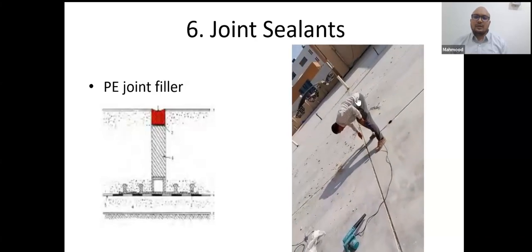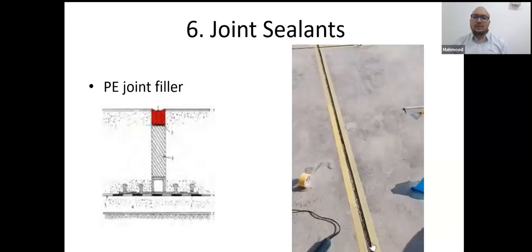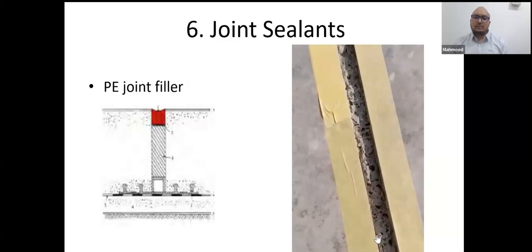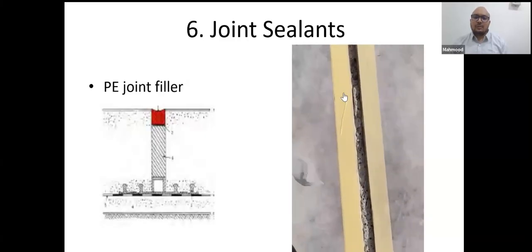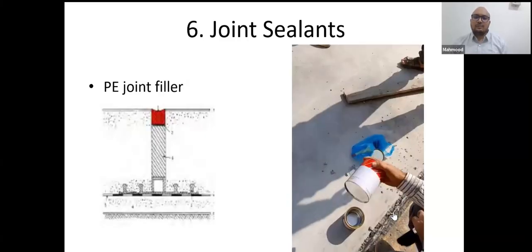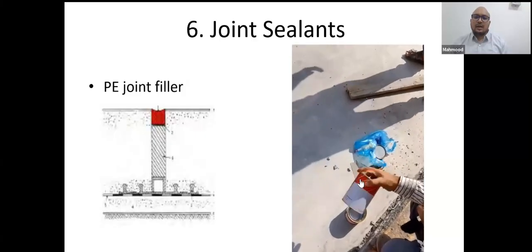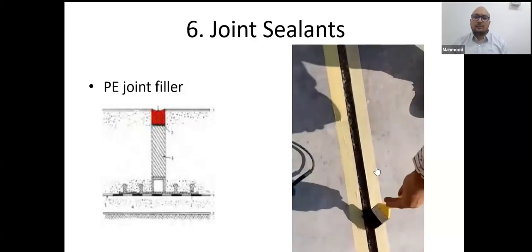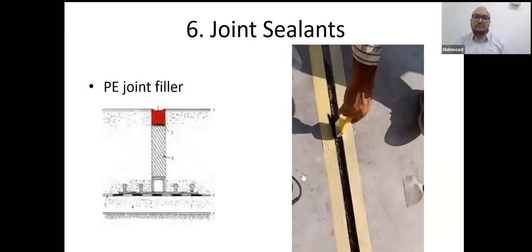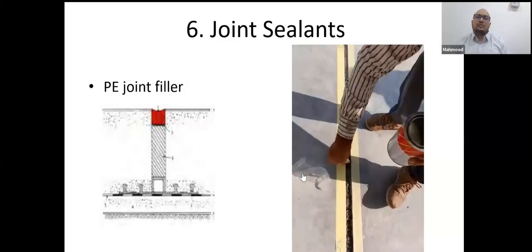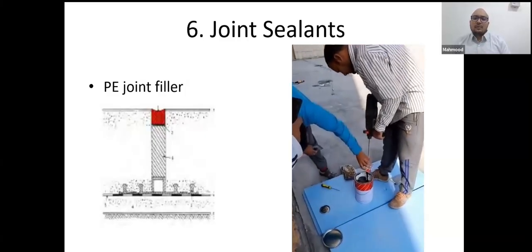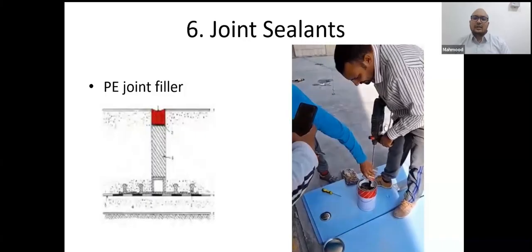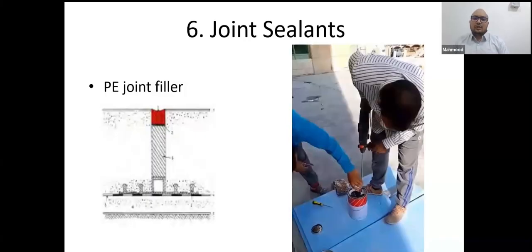This is an exposed area, exposed to sun. They're preparing the joint. They're putting masking tape. Base and hardener, they're mixing it. Primer, they're applying the primer by brush on the joint where the sealant will come. They're mixing the polysulfide sealant with the curing agent.